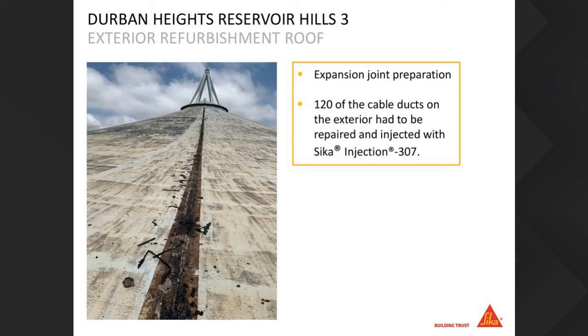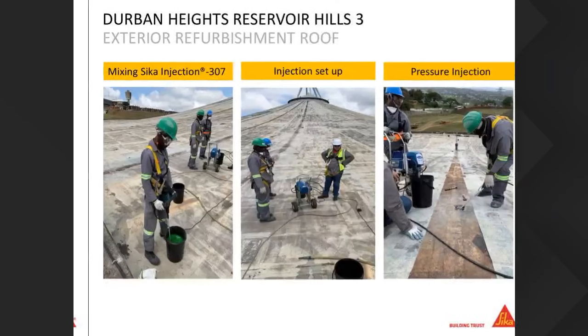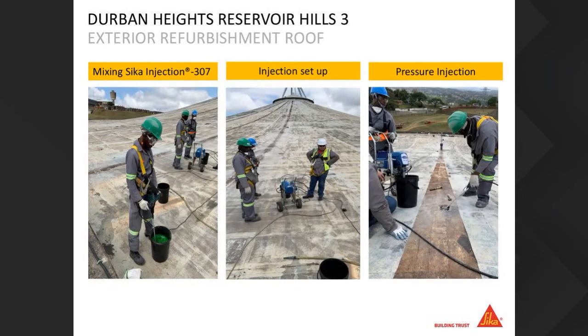So we then chose our Sika Injection®-307, which has an extremely low viscosity, and it's also passivating to steel. So it's got passivating properties, and that's why this product was selected. Here, on just a bit of exterior photos that I want to show you, the guys on the left-hand side are mixing the Sika Injection®-307. Some unique properties, like I already mentioned: passivating towards steel, very low viscosity. It's got a viscosity of 7 millipascal seconds.